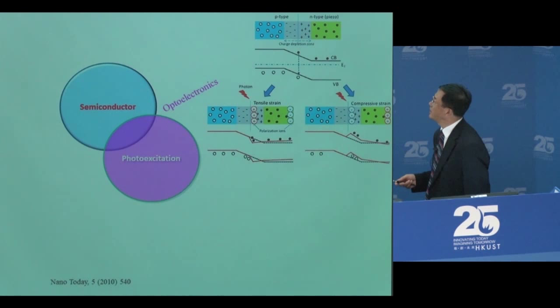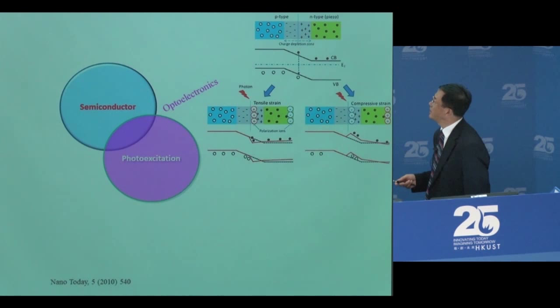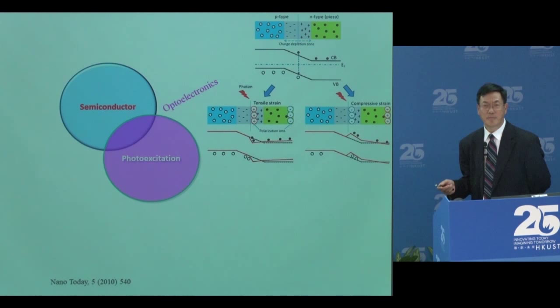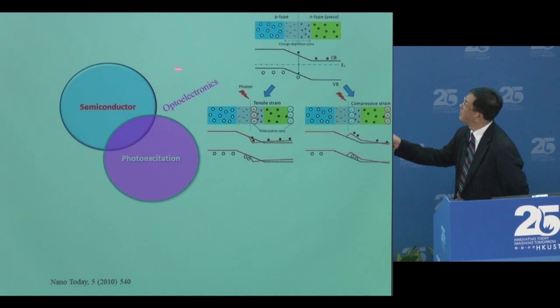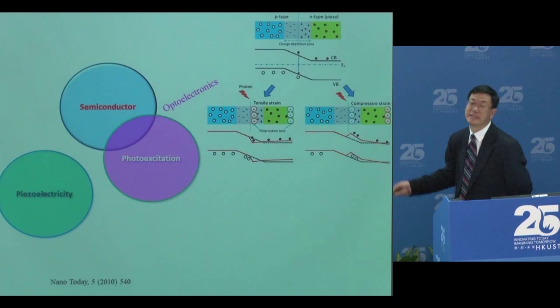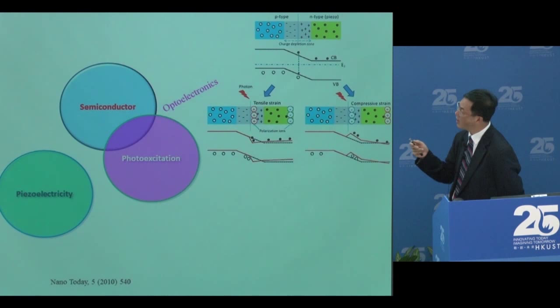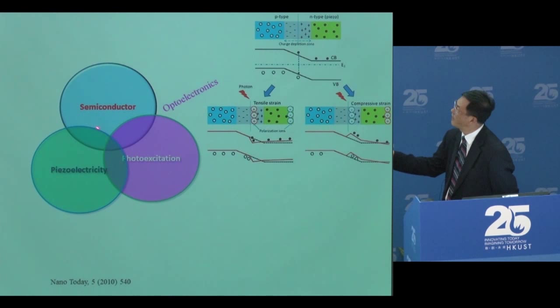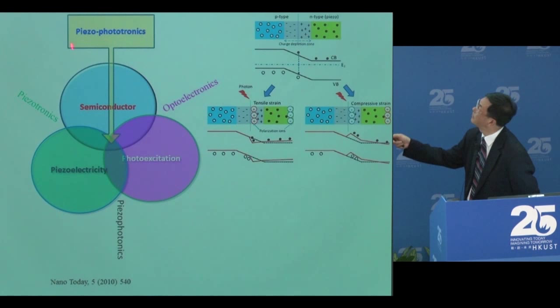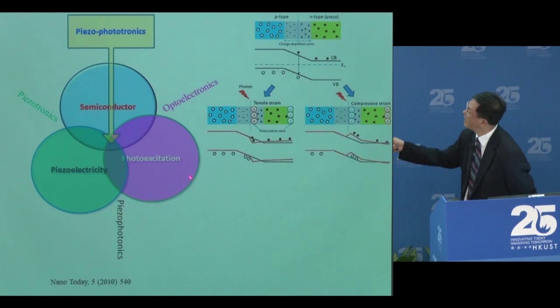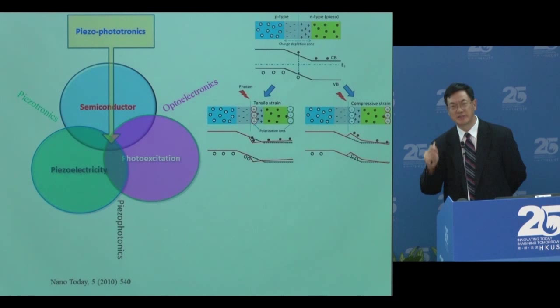Over 10 years we studied a number of effects. Why hadn't people thought about this before? Probably due to the material system they used. For optoelectronics, people chose III-V or II-VI compound semiconductors; for piezoelectricity, mostly PZT — always choosing the best material for one purpose. But if you use one material like zinc oxide or gallium nitride and bring properties together, you get new overlap. Coupling between semiconductor and piezoelectricity is piezotronics; three-way coupling is piezo-phototronics. Can piezoelectricity itself produce photon emission? I want to present that next.